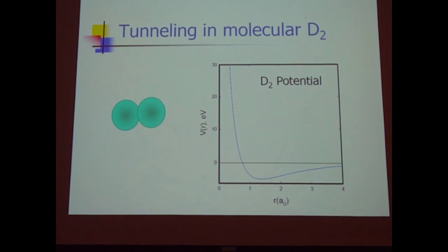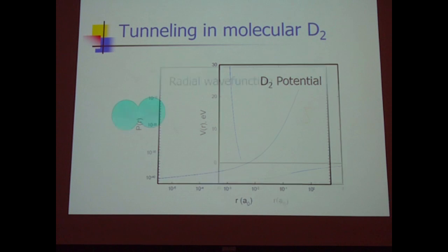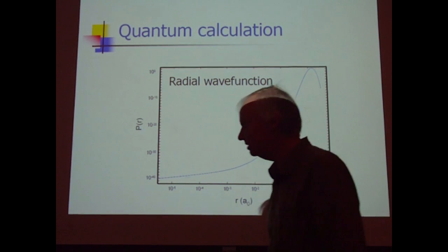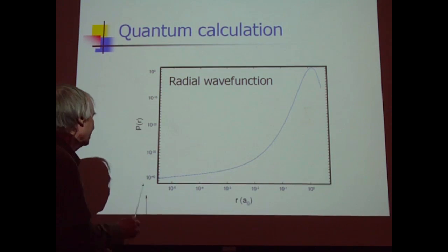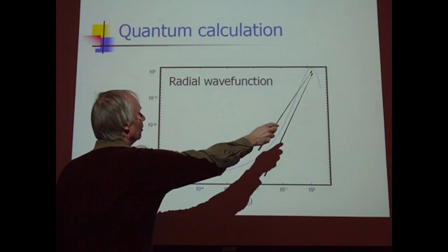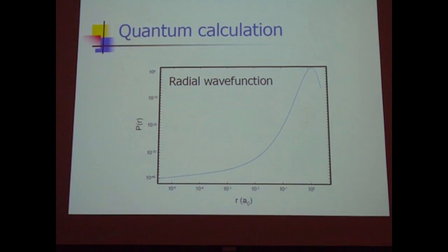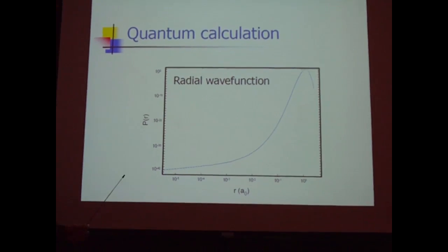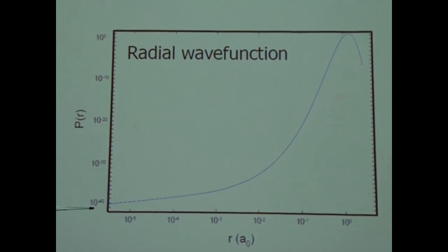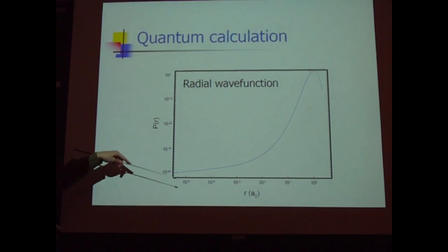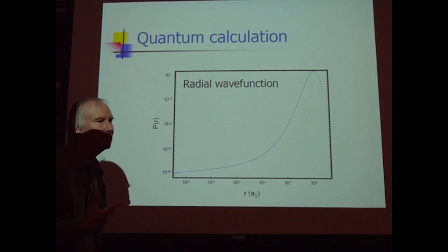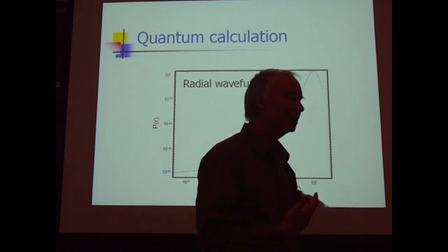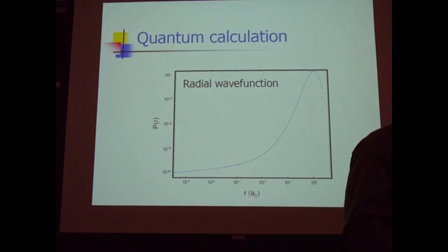So we recall on day one, we calculated the screening for the D2 molecule and penetration. This is 10 to the minus 40th, and this is near 1, so you might look at that and say, well, you get 40 orders of magnitude, but there's a radial factor because this is P instead of R, so it's actually 10 to the minus 35. So basically, the molecule is consistent with the 10 to the minus 35 tunneling number, but if you have screening, you're going to get more penetration.